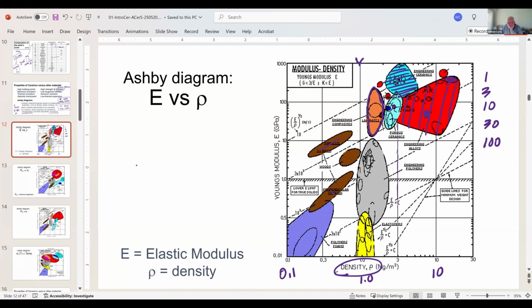Polymers, by comparison, all sit down here. Polymer foams are here. Here are engineered polymers. What you should notice in this figure is that my engineered polymers have a maximum elastic modulus somewhere around 10 gigapascals, and my ceramics have a minimum elastic modulus of somewhere close to 200, 150 or so. Engineering alloys span that difference a little bit, starting somewhere around 20 gigapascals, up to probably about 400 gigapascals.